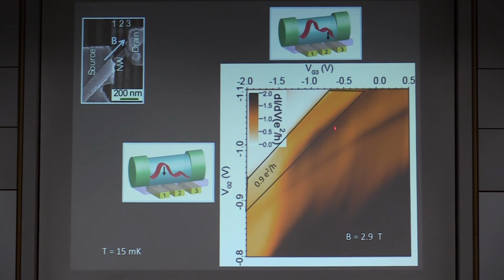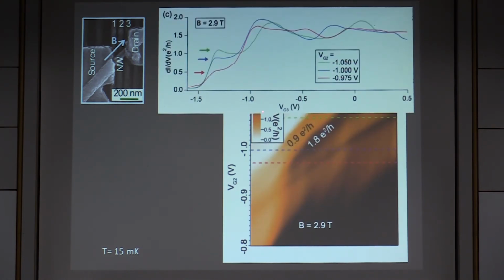In fact, if you look in this regime, the conductance is around 0.9 e²/h, and in this regime it is around 1.8 e²/h on average. But there are some fluctuations of around 10–20%, which indicate that the system is not exactly free of some backscattering effects. In fact, there are resonances that evolve mainly in this direction that could be associated with some localized state. What I want to show you is that you can, for example, vary this gate voltage G2 and choose one voltage, for example this blue line, where there is a nice plateau in conductance. Well, it's not exactly 1 e²/h. There's some finite transmission at the level of the contacts, but it's 0.9, very close. It's a pretty flat plateau.